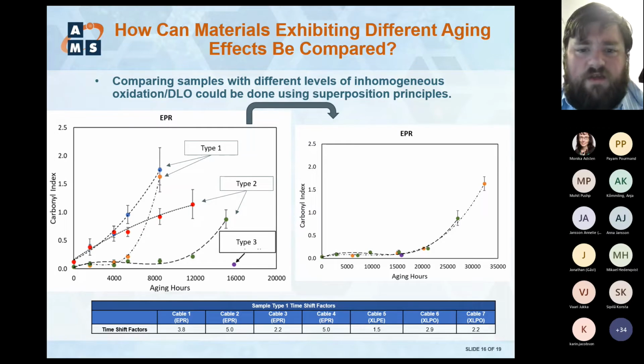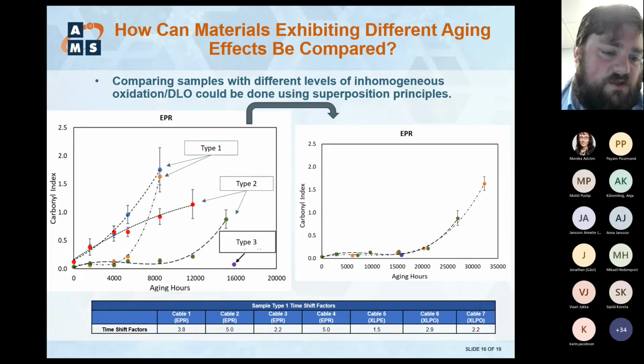So one method we've done, and this is applied for different ones, is if you look at the middle samples, which are hopefully away from the surfaces, and you don't have these dissimilar material interactions and driving copper catalytic effects or something like that, you do get profiles that match pretty well when you apply superposition principles. So we did that for a few of our samples. We were able to superimpose, or basically apply a shift factor to, the orange and green data points to get them on the same playing field as the purple data points.